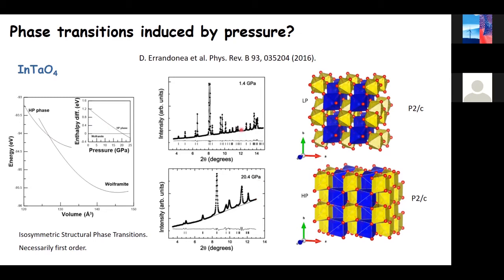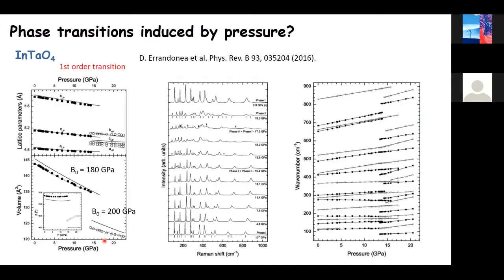You can see here Rietveld refinement with the low pressure phase and the high pressure phase. And so the transition goes from the same space group, P2/c to P2/c, so it's isosymmetric. Then according to the theory of phase transitions, the transition should necessarily be first order. This is a first order transition as in indium tantalate. We confirm it is first order here by this volume change.